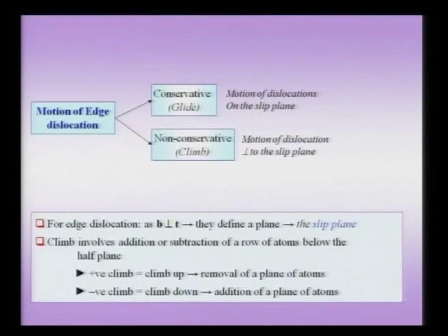Now, as I pointed out, the motion of an edge dislocation can be conservative. The motion of a dislocation on a slip plane is called conservative motion, and if the edge dislocation moves perpendicular to its slip plane, then this process is called climb and it is a non-conservative process. When I say a non-conservative process, that means that it involves mass transport. Motion on the slip plane just involves shear stresses, but motion from one slip plane to a parallel slip plane would involve mass transport, and we will see how that is so. Because now the climb process,